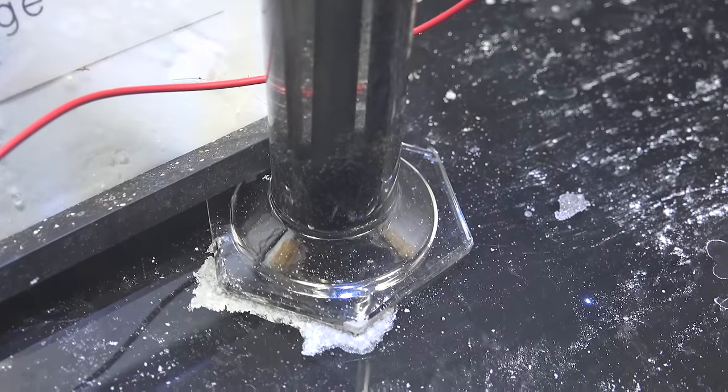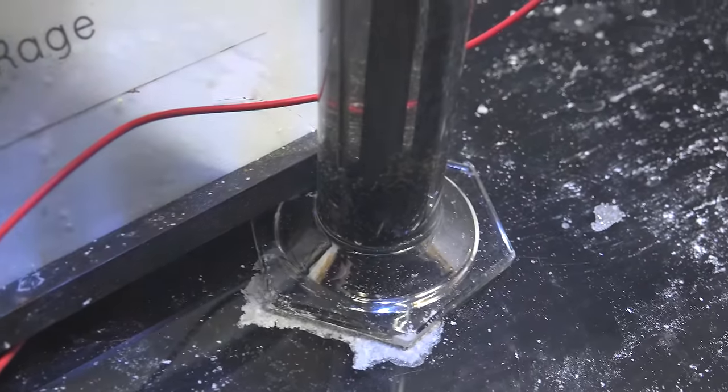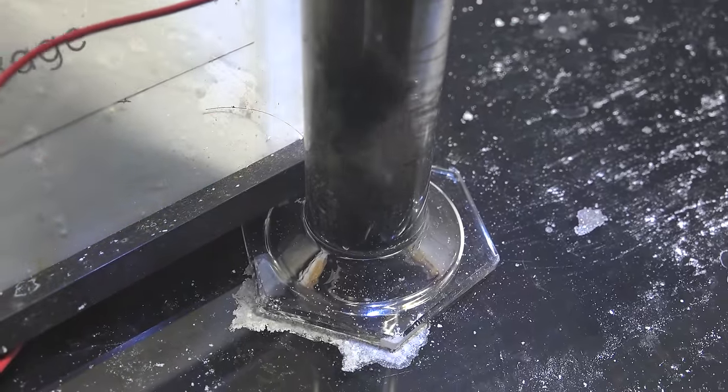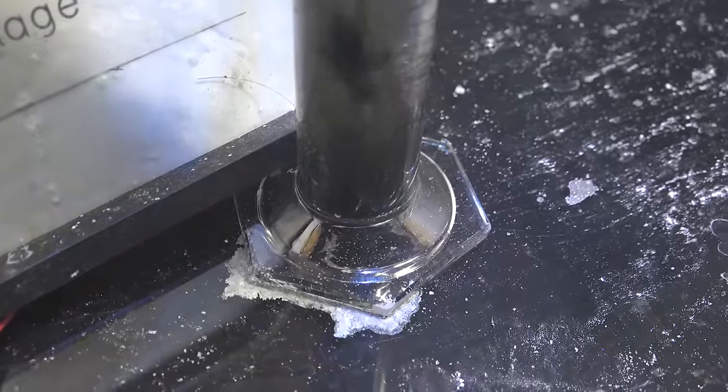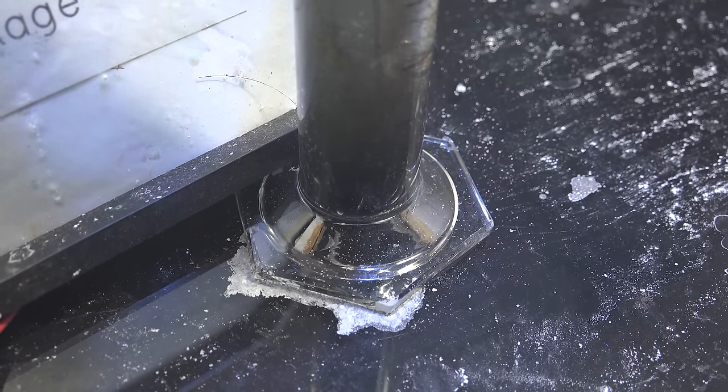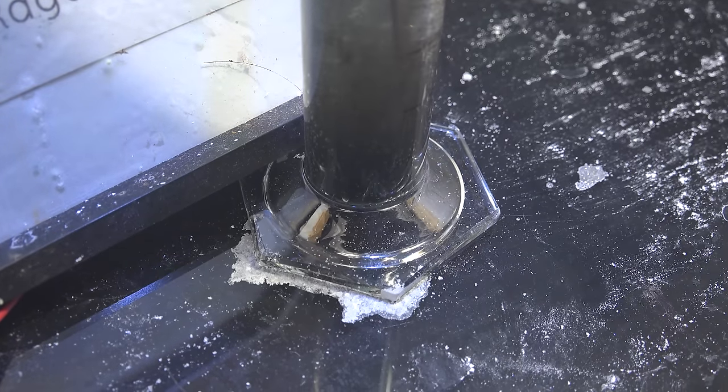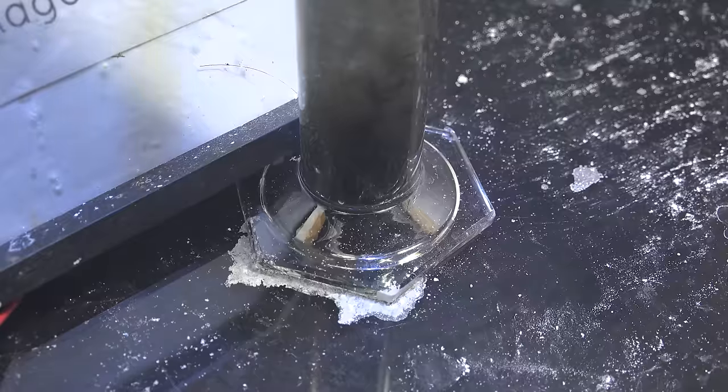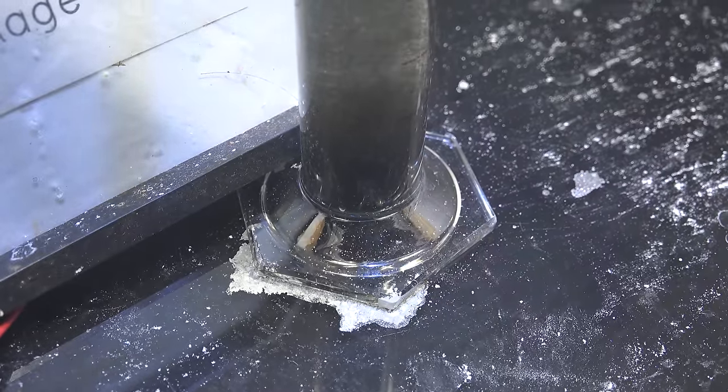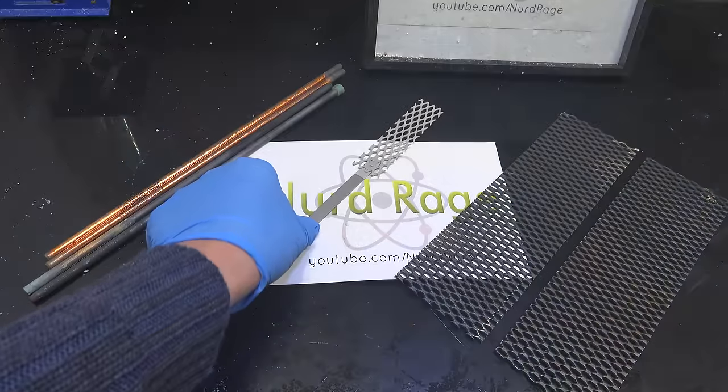Anyway here it is after running it for several hours. That's precipitate potassium chlorate contaminated with carbon. While it looks bad, if you just want your potassium chlorate for fireworks and other pyrotechnic uses then a bit of carbon contamination is inconsequential. Carbon electrodes tend to slough off the most during the first few days of use, but then taper off. So subsequent runs will be somewhat cleaner than this. If you want it pure you can still re-dissolve it in hot water and filter. Alternatively you can use a better electrode.